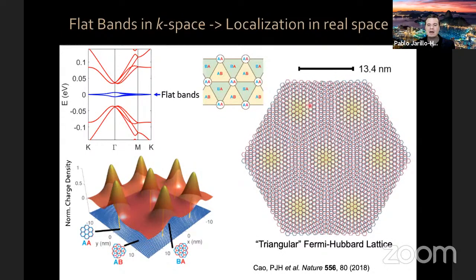This is going to form now our triangular Fermi-Hubbard lattice. We're going to put our electrons here. These AA regions are spaced by about 13 nanometers. And I put triangular in quotes because in reality, this is still a honeycomb lattice because the AB and BA domains are not identical. So this still has a honeycomb structure.